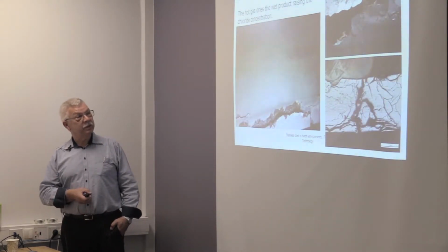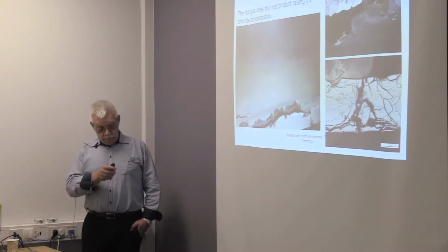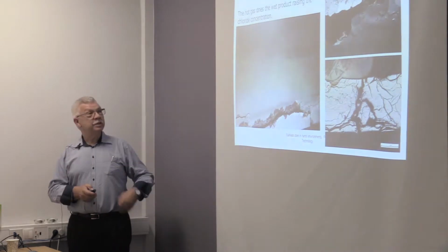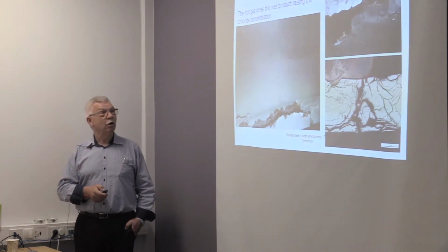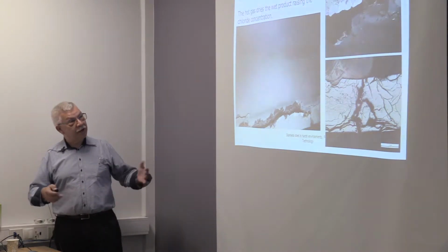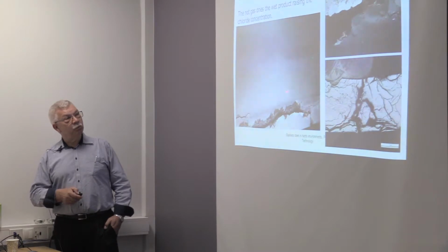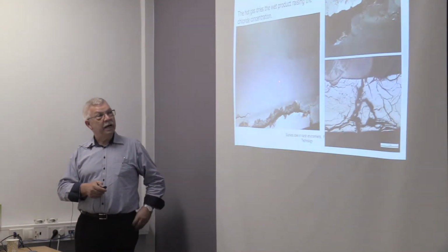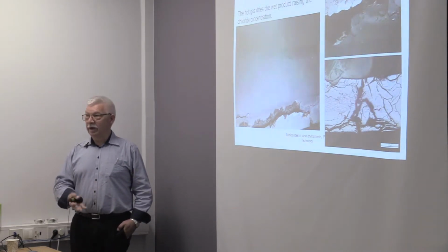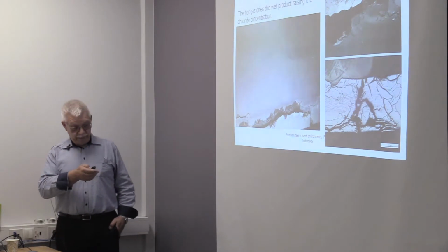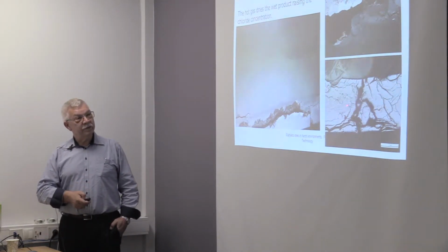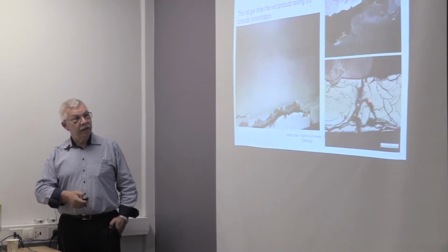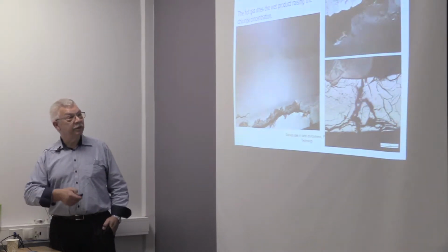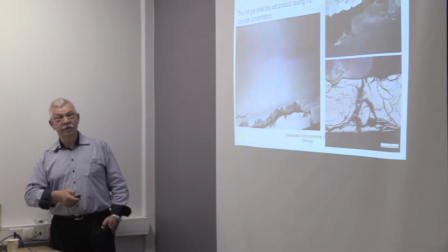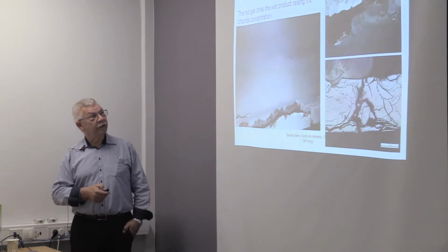Another example, this is a dryer where we have a product with chlorides, with salt in it. It's wet, it's going to be dried, so it meets hot air in this tank or chamber. And on the surfaces, this wet material is depositing and drying up. And in that process, the chloride level is increasing to a level where we can have stress corrosion cracking. And as you can see, that's a very bad situation because there are numerous cracks going branched into the material. And repair, yeah, that's cutting somewhere up here and somewhere down here because this area is totally destroyed from cracking.